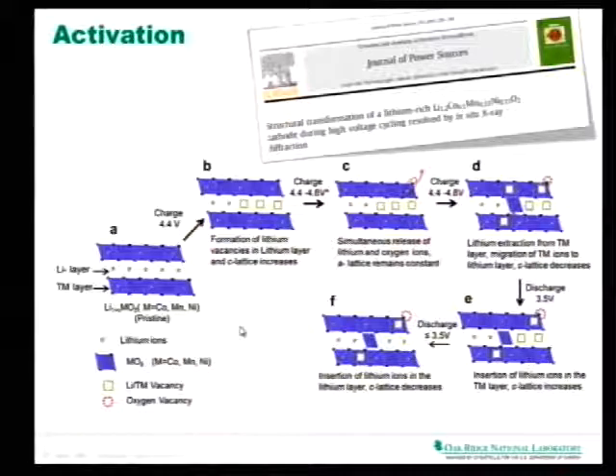So you have a nickel manganese cobalt oxide here, which has a nice layered structure. You have your lithium layer here. Here's all the lithium you can access. Here are all the transition metals, right? In your transition metals, in this particular case, there's also quite a bit of lithium in there too, but let's ignore that for now. You're charging it up, so you pull the lithium out, and you create empty spaces. You create vacancies in there, which allows you to later on put the lithium back for discharging.